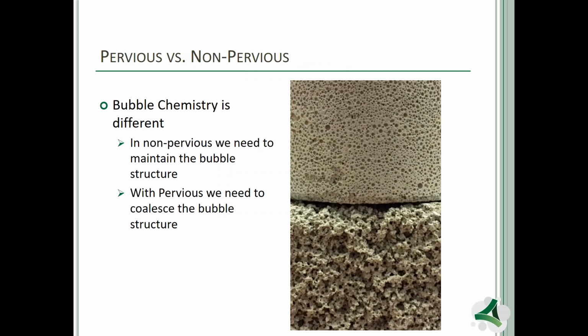The difference between pervious cellular concrete and non-pervious cellular concrete is within the chemistry of the air bubbles. When it comes to the non-pervious cellular concrete, we want to maintain the structure of that air bubble, whereas with the pervious cellular concrete, we want those bubbles to coalesce or unite to create open cell technology. Your concrete, water, foam mix designs are going to be identically the same. The only difference will be the chemistry of that air bubble.